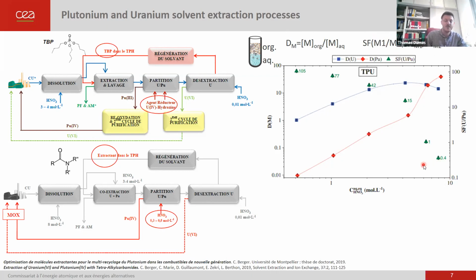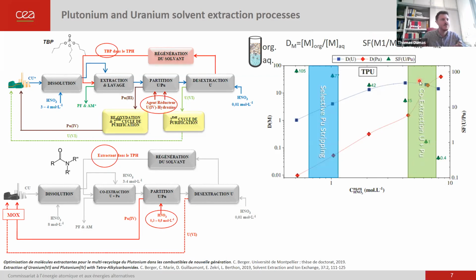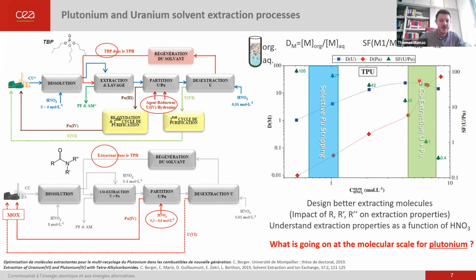Okay, so the process works this way. You first go to high acidity where you have good distribution ratio for both elements, and then you go down to this position where the plutonium is less extracted, and then it will go down to the aqueous solution. So what we want to understand here is what happens if you change the design of these molecules on this distribution ratio coefficient, and what happens also while you are changing the acidity in the aqueous phase for the plutonium structure in the organic solution.